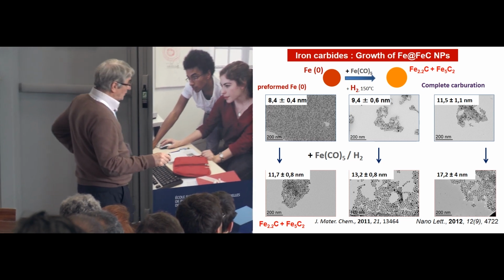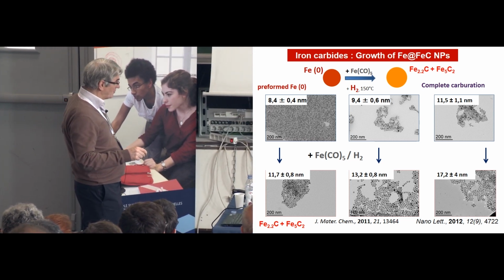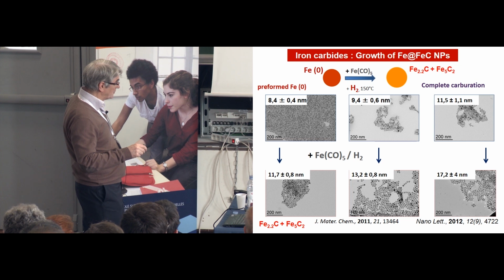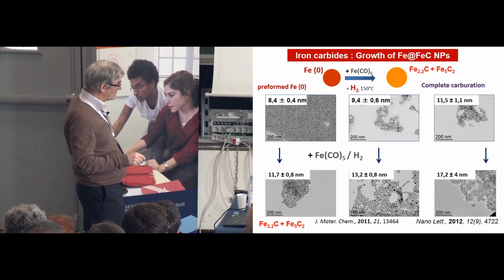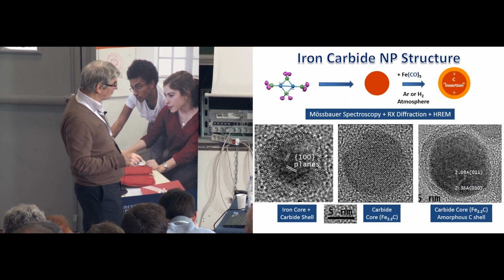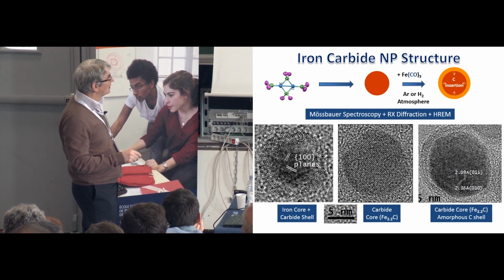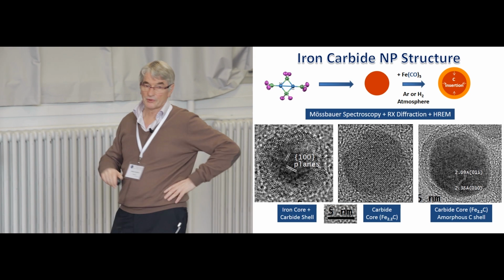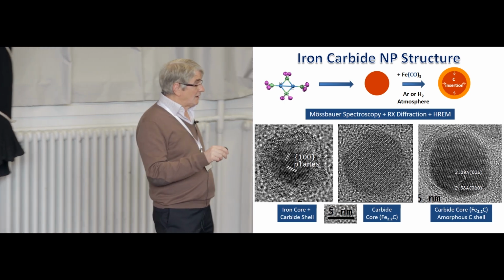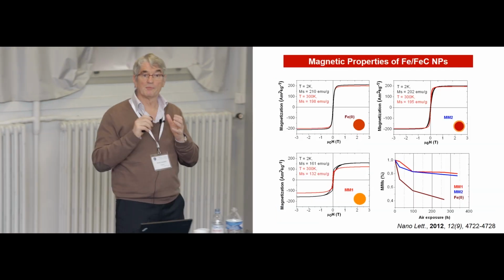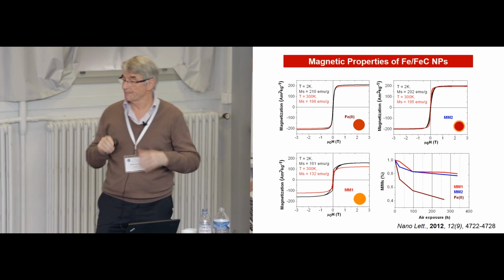These are the core shell, full carbide, and also we can grow graphene sheets around. The two which have carbide are air stable. This is loss of magnetization as a function of time. Iron zero loses 60% of its magnetization rapidly, and the two others only 20%.